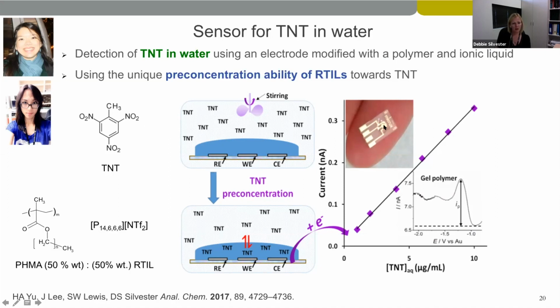And the gel polymer, in this case, because we were dipping this directly into water, it had to be very hydrophobic. So we used a polyhexyl methacrylate polymer with a P14666 ionic liquid. This gel polymer at a 1-to-1 mixture was drop cast onto the electrode. And then we had a water sample containing TNT. The electrode goes into that sample. We stir the solution, and then the TNT pre-concentrates into the ionic liquid gel polymer.